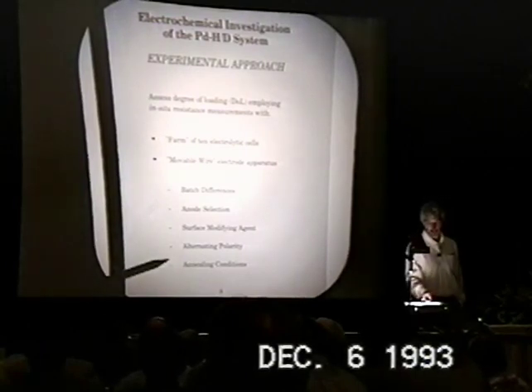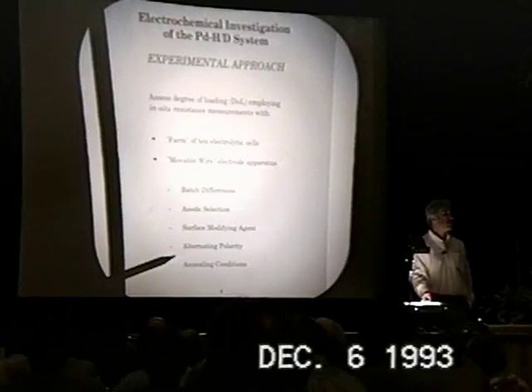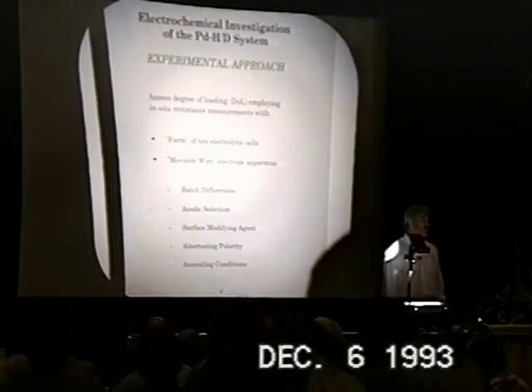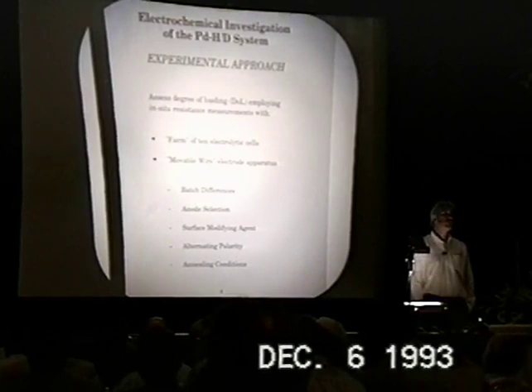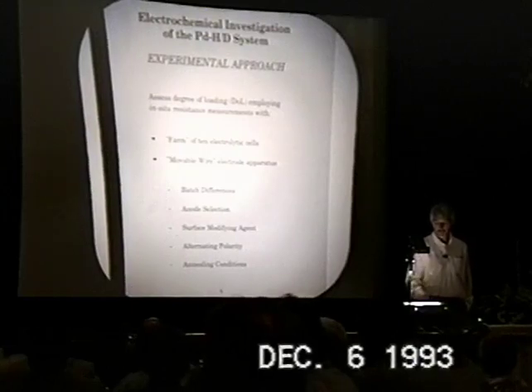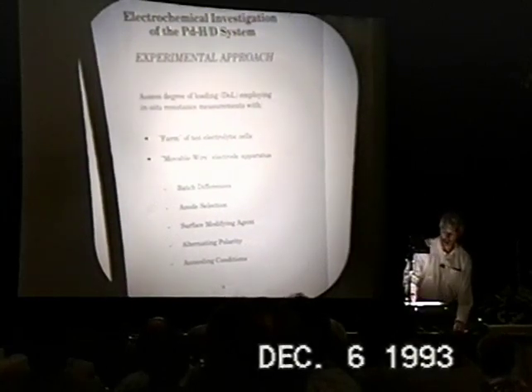I'm able to confirm that this alternating polarity method does indeed cause increased loading of hydrogen into the lattice sites, which give rise to the resistance change that we measure as a determinant of loading. I also want to speak a little bit about annealing conditions.